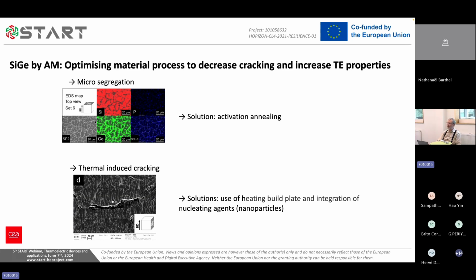First, to reduce the material segregation, by activation annealing, and to reduce the thermal-induced cracking. So there are two ways of doing that. To use a heating plate in a 3D printing machine, this is a common solution, and to use nucleating agents. And this is also something that you find in state-of-the-art. It works for aluminum, for instance. So this is work in progress, and this is why we have this PhD student. And this is being addressed in our FAST project.